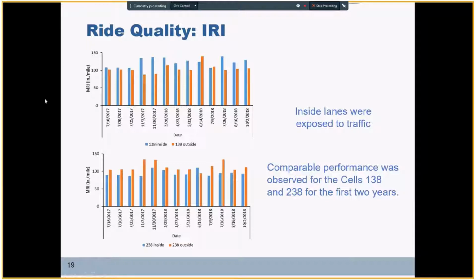The inside lanes, shown with blue colored bars, are the lanes where we had controlled traffic on low volume roads. At different time intervals from late July 2017 up to early 2018, we have had IRI measurements. For the first 3 measurements we have almost constant data in July, but after a couple months, starting with November data, there's a slight increase in IRI values, with almost constant observations afterward, no significant change after that. As you can see from these two graphs, we had really comparable performance for both cells 138 and 238 for the first 2 years of monitoring.